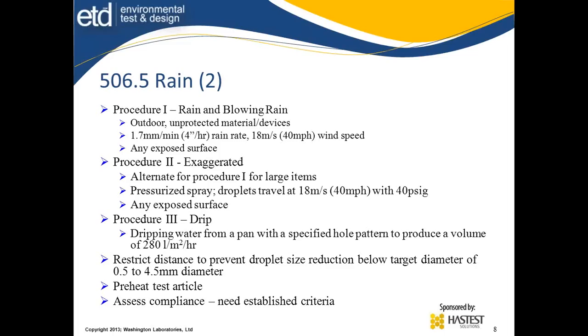It's an exaggerated test that can be used as an alternate for procedure 1 for large items where you use a pressurized spray, like a spray cleaner. The droplets travel at the same speed associated with a 40 pound per square inch pressure, and in order to get the rate and droplet size, you'll need a certain head size for the sprayer's head. Again, you apply it to any exposed surface that would be exposed to the blowing rain or this pressure.